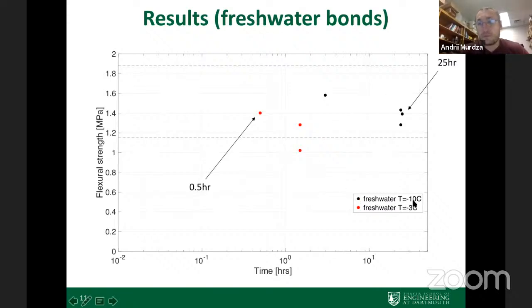We did this at two temperatures, at -10 Celsius and -3 Celsius. These two vertical dotted lines show the upper and lower band for the measured strengths of the intact ice, the ice without a bond, just to see where our new data points fit. As we see, all the data fit within this range pretty nicely, with one point slightly below. There could be some issues with the alignment, because in 4-point bending the sample is very sensitive to it.